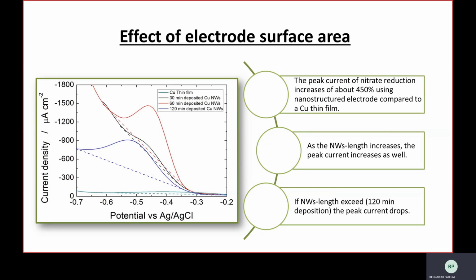Using a 60 minutes deposited electrode, the signal enhancement is much more pronounced, while interestingly, the peak intensity drops using a 120 minutes deposited electrode. This is probably due to the membrane interconnections. Indeed, as I said before, increasing the deposition times, the nanowires became longer but even more compact, and thus the wettability of the electrode decreases. In order to have a compromise between electrode wettability and surface area, the deposition time was set to 60 minutes.